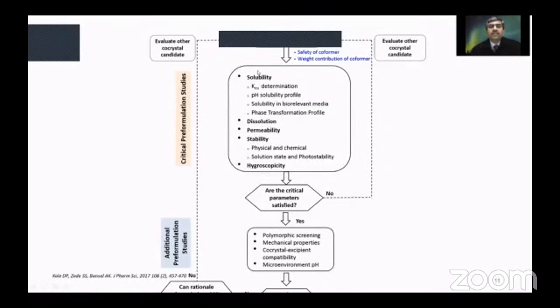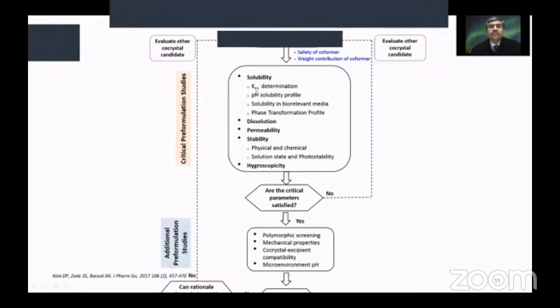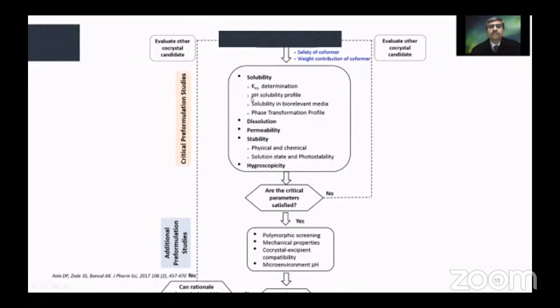The first most important aspect that we need to evaluate is that of solubility, and within that we will also look at the eutectic constant determination, because this tells us what is going to be the duration of the solubility advantage during the dissolution stage. pH solubility profile, solubility in biorelevant media, and phase transformation profile are all important components of the solubility studies. Thereafter, we should look at the dissolution, intestinal permeability, physical and chemical stability, solution state and photostability, and the hygroscopicity of the co-crystal candidates.